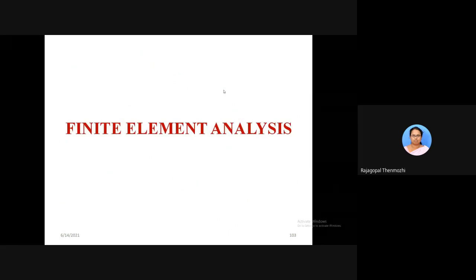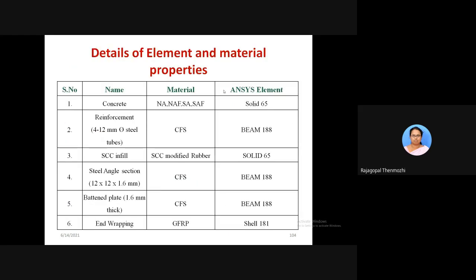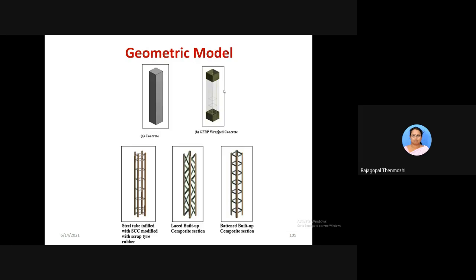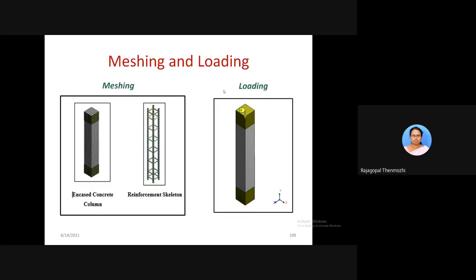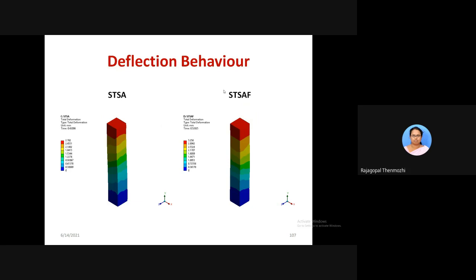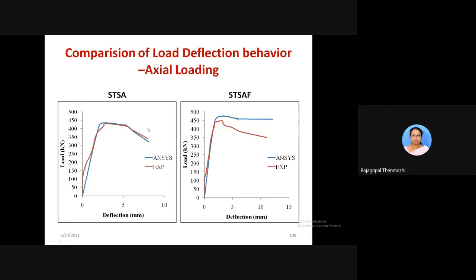When we go to the finite element analysis, the composite column is modeled using ANSYS. For concrete, we have used the Solid65 element. For reinforcement, the Beam188 3D element, and for the infill also it is Solid65. Steel angle sections again are bending elements, so Beam188 has been used. These are the models we have made, and this is the meshed pattern, and after the load is applied, this is the deflection behavior in the linear state, and this is the ANSYS and experimental comparison. We could get a very good comparison between the experimental and the ANSYS results.